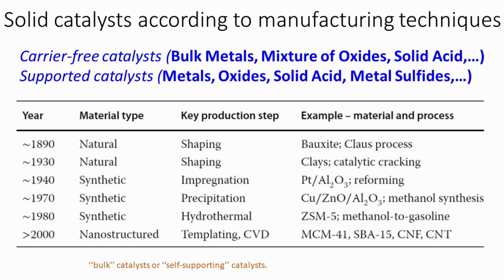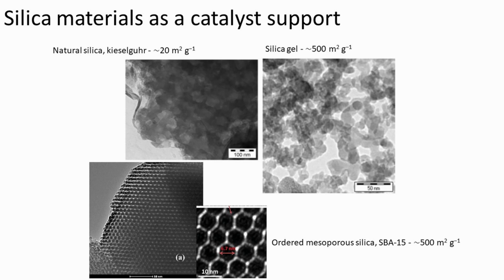Using micelle templating, nanostructured silica such as MCM-41 and SBA-15 and other oxides have been produced during the last 20 years. Using chemical vapor deposition techniques, nanostructured carbon materials such as carbon nanofibers and carbon nanotubes have been produced and explored as catalyst supports. The slide presents three generations of support materials, that is, natural silica, Kieselguhr, silica gel, and ordered mesoporous silica. Moving from natural to synthetic materials has greatly improved the control over composition and texture of the support.